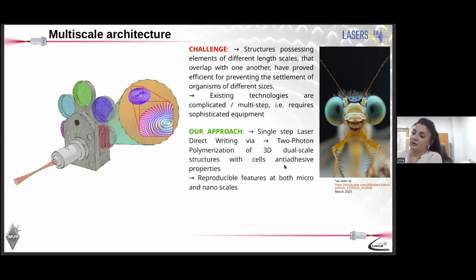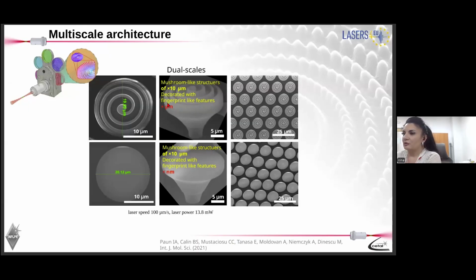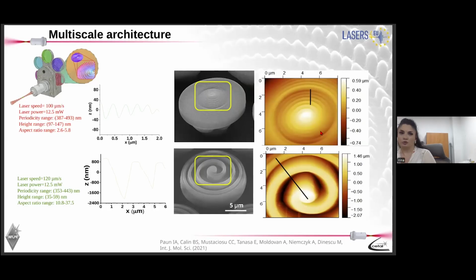In our case, the advantage of our 3D printing technology is that it's a single-step procedure that enables us to provide microscale structures and, right in the same processing step, to get some nano features on top. Here are two examples of microstructures in the shape of mushrooms, because we also want to make them a little bit water repellent. They are decorated with fingerprint-like structures. On the top part, we have microstructures here on the fingerprint, here nanostructures, which you will see better in the atomic force microscopy image.